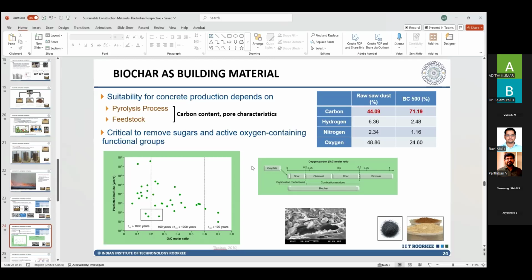To do that, you use what's called an oxygen to carbon molar ratio. You test that, you find out how much oxygen is present in comparison to carbon. The less the oxygen, the better it is, because it's the oxygen that creates those reactive functional groups which might do unwanted reactions. So the lower the oxygen to carbon ratio, the higher the stable life of the char is. So usually we prefer 0.3 or below, which is very easy to obtain through normal pyrolysis itself.